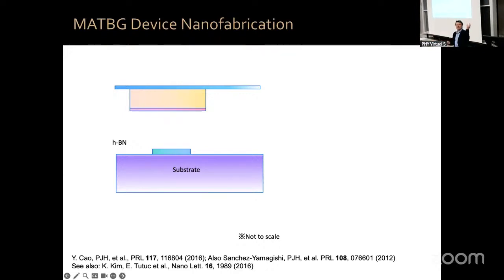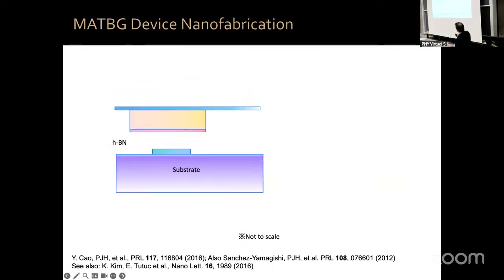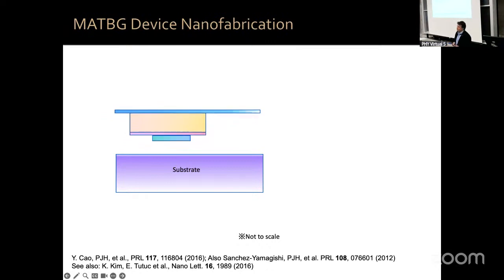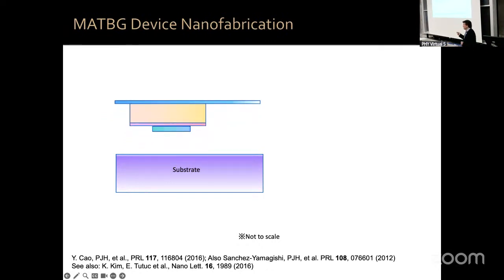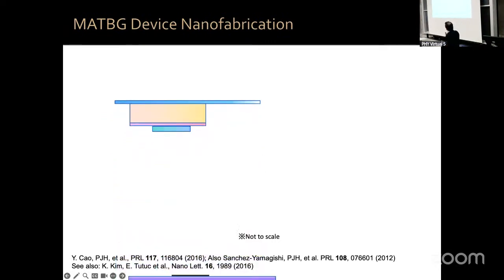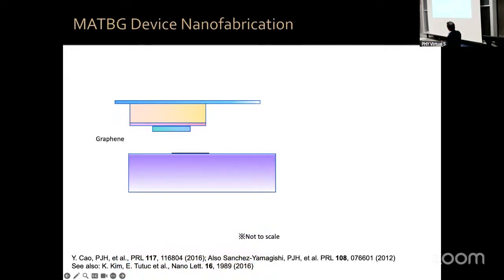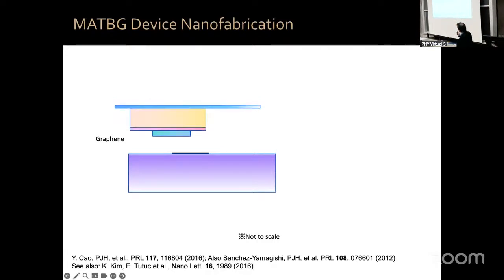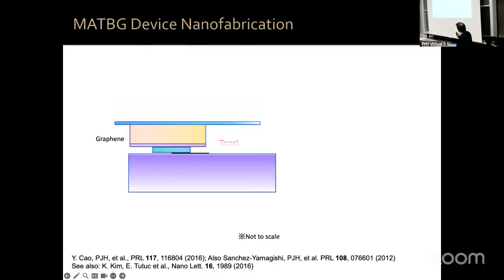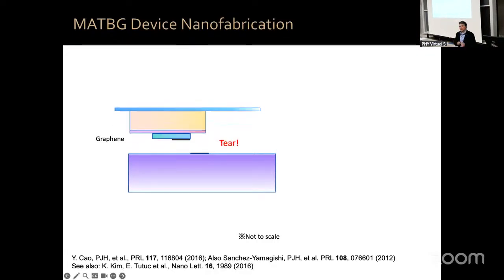Maybe something like 10 nanometers thick or so. So we come with a sticky polymer and we pick up the boron nitride substrate. Then we bring a different substrate with a graphene sheet on top of it. And we position our hexagonal boron nitride sort of halfway on top of this graphene sheet.